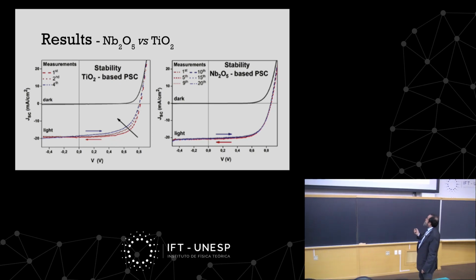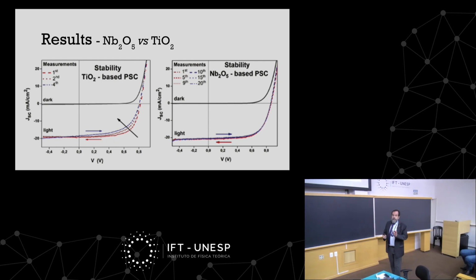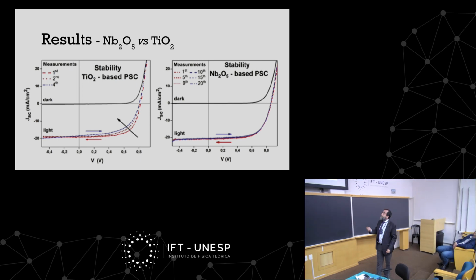But look here. I just changed one little layer. All is equal, but I changed the compact TiO2 to niobium oxide. And then suddenly, I make one measurement, 20 measurements, and I basically don't see anything. And it doesn't matter if I'm going up or down. The hysteresis disappeared. So I don't have hysteresis, and I don't have degradation, just by changing one little layer.